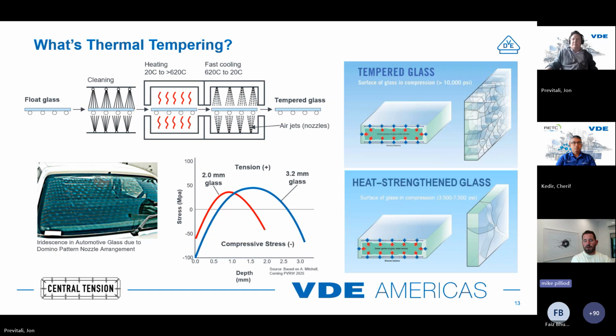To the question of 2 millimeter glass being the thinnest front surface, that's a question of how much stress do you need to put into your glass. There eventually will be a fundamental limit based on thermal tempering using soda lime glass. As you heat it up and cool it down, near 2 millimeters it gets very difficult to induce the right level of fast cooling so the middle of the glass can continue to shrink. It's why chemical tempering and other things are used in the cell phone industry and consumer electronics, because as you get sub 1 millimeter, it almost becomes physically impossible to cool the glass fast enough without thermally shocking it.